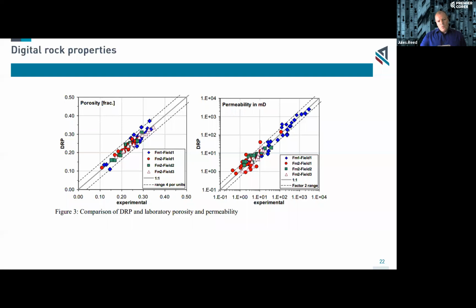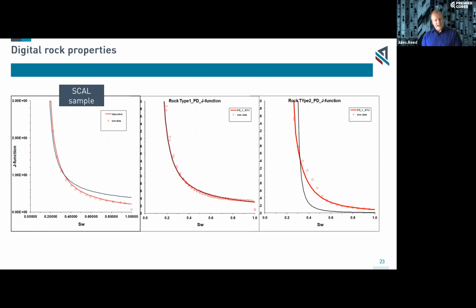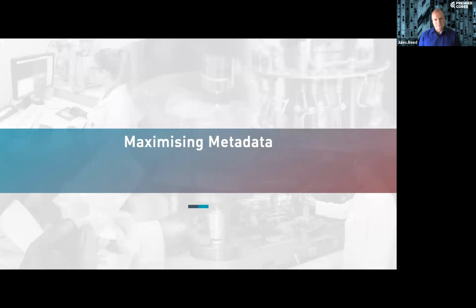So once you've got a pore map, you can begin to predict or history match things like porosity and permeability from those data. It may not be perfect, and it will require some legacy data to history match your current sample data to some previous data, so that you're tuning your model from that system. But once you've tuned the model, you can then begin to do multi-phase rock properties, something like a capillary pressure curve. In this particular case, this was one sample that, within the heterogeneity of the sample, had two different rock types. We're able to sub-sample the two different rock types, get the capillary pressure data for those, and then put those together into the larger scale sample. So those are things we can do with our legacy core.